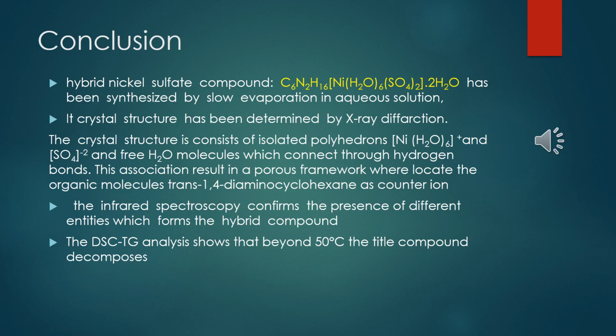The new hybrid organic-inorganic nickel sulfate compound with trans-diaminocyclohexane acting as structure directing agent has been synthesized by slow evaporation in aqueous solution. The crystal structure has been determined by X-ray diffraction. The crystal structure consists of isolated polyhedra which connect through hydrogen bonds. This association results in a porous framework where the organic molecules are located.